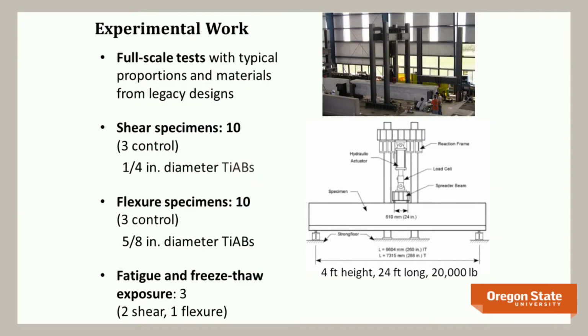We've got 10 different shear specimens, 10 different flexural specimens, and we have 3 specimens that are kind of unique, where we are subjecting them to high cycle fatigue at the same time that we're subjecting them to freeze-thaw exposure, because we're interested not just in this immediate performance, but also long-term durability of what we're doing.